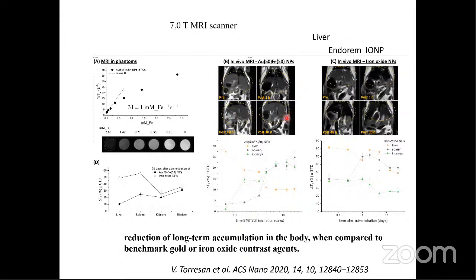We have also studied the biodistribution of the nanoparticle. It is not as clear as with gold, but if we compare the gold-iron nanoparticle with the iron oxide nanoparticle, we see a larger signal for the iron oxide nanoparticle. This is ENDOREM, an iron oxide nanoparticle that is commercially available. There is more persistence for this nanoparticle than for the gold-iron nanoparticle. So we understand this study as an indication of a reduction of long-term accumulation in the body when compared with benchmark gold and iron oxide contrast agents.